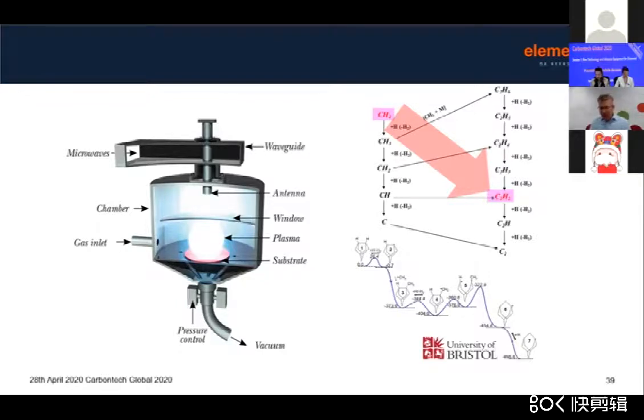So we put out a diagram that explains to people the fundamentals of how you grow diamond. And we would say that for our reactor this diagram is accurate in that we do use the microwave CVD process. We do actually couple into our chamber via a waveguide and an antenna system. We do use a window to make our vacuum chamber integral. And then we do grow on a substrate in a resonance cavity.